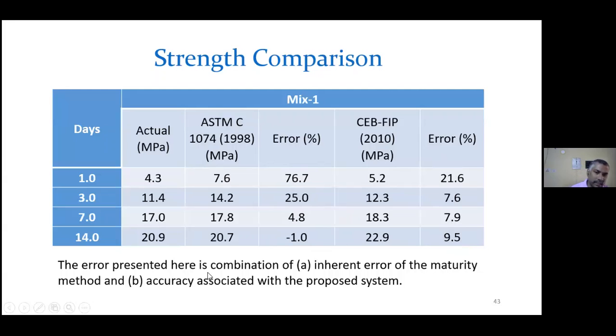So you have to note here that this error is not the error of our system alone. There is also some error associated with the maturity method that is outlined in the code. So the code equation also has some problems, and some problems may be there in our implementation of that. So the error presented here is a combination of the inherent error of the maturity method and the accuracy associated with the proposed system. But still, if you compare the actual value and the predicted value, you get very close to the actual value, right? The predicted compressive strength is very close to the actual values.